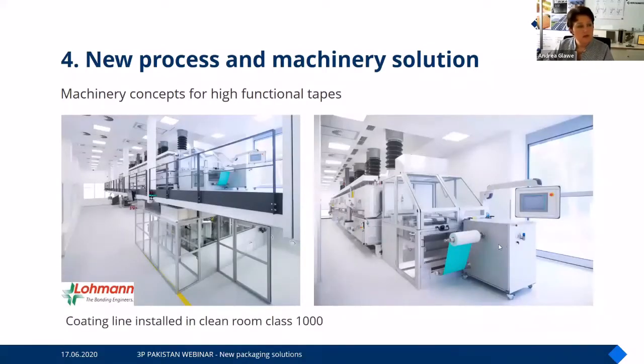Here you see a coating line which we supplied to Lohmann. Lohmann is producing adhesive tapes for lamination, but also for just simple applications. This is also an example of having such a machine running completely in a clean room atmosphere to apply coating layers with a very high precision, without any pollution in the process, to get very perfect materials at the end. So this gives you an impression that the design of the coating line is always adapted to the product which has to be produced with the machine.